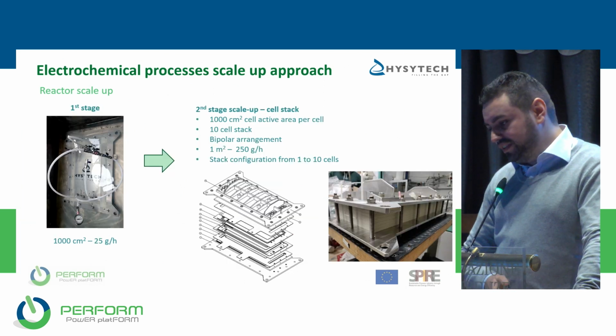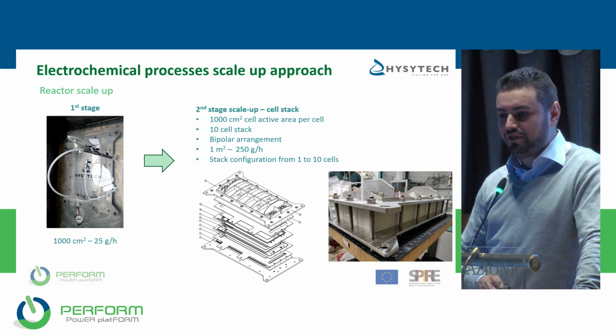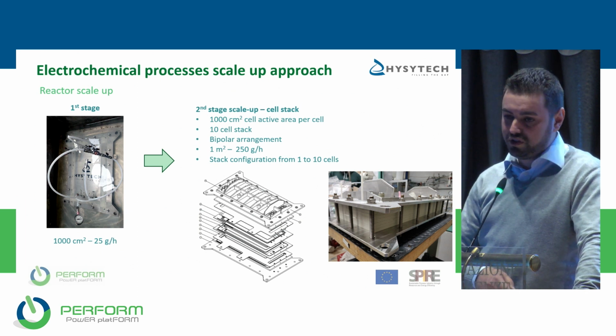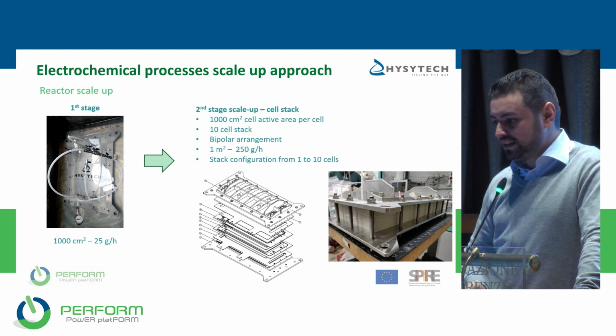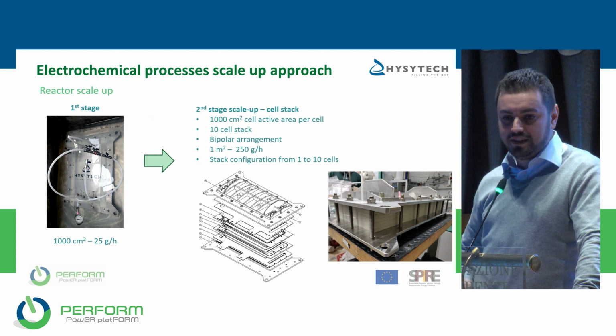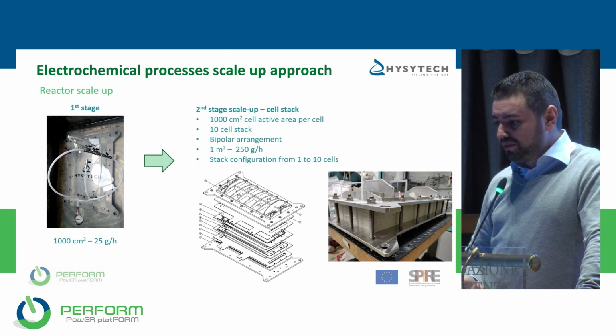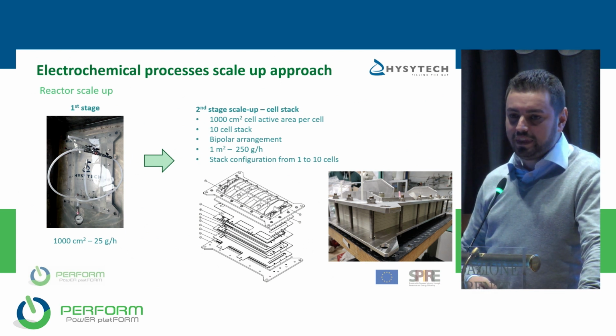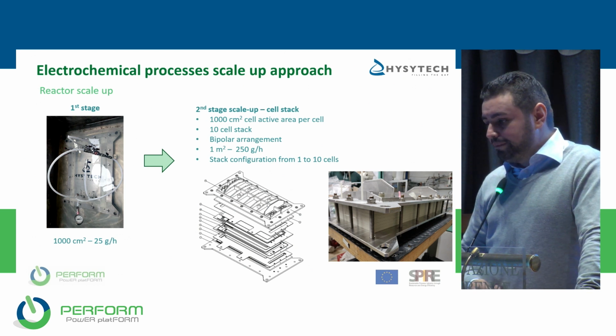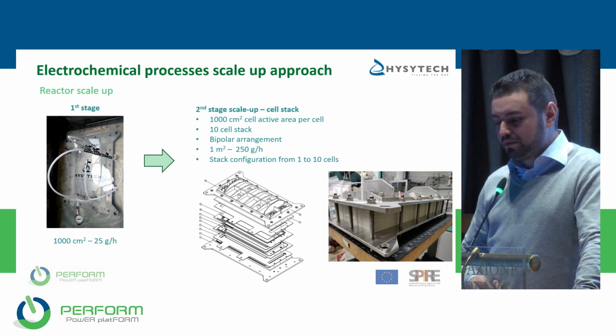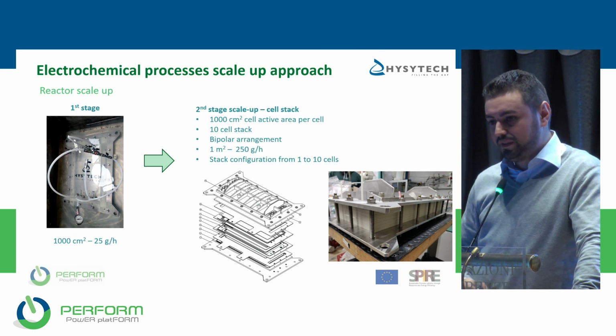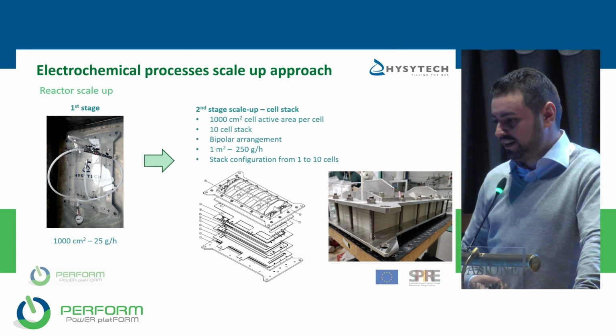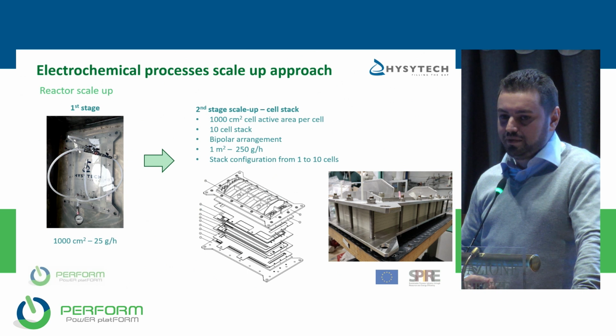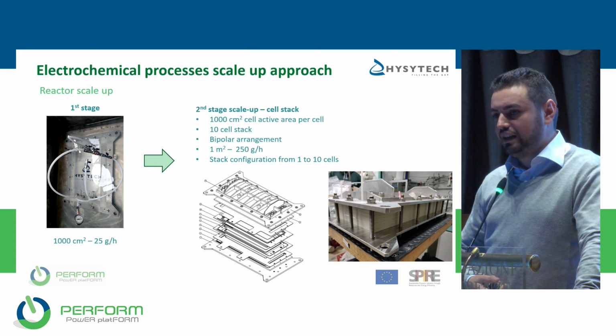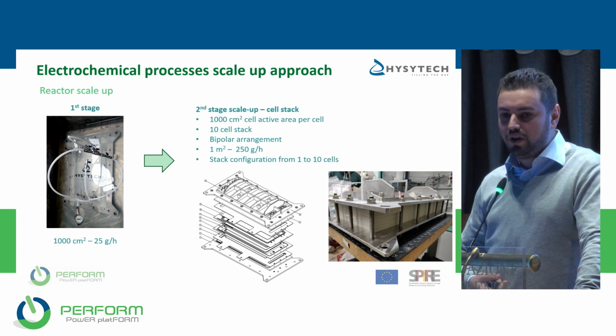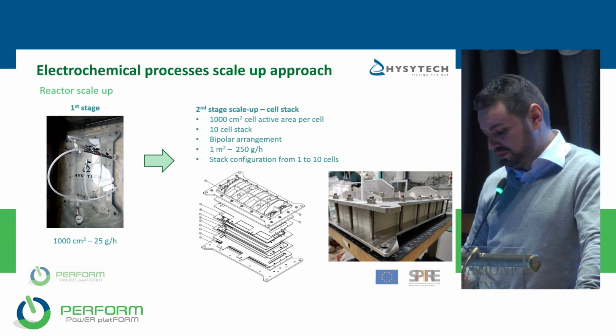After a bit of back and forth between us and the partners, receiving all the feedback about how to build the cell, which arrangement was better, and so on, we moved to the second stage of upscaling of the reactor, that is building a cell stack. For the cell stack, we built a bipolar arrangement stack, which means that all the cells in the stack are electrically connected in series. With 10 cells, we reached the 1 square meter electrode active area. Furthermore, this stack is modular. You can replace the electrodes relatively easily, and you can also work with a different number of cells in the stack, from 1 to 10 cells.